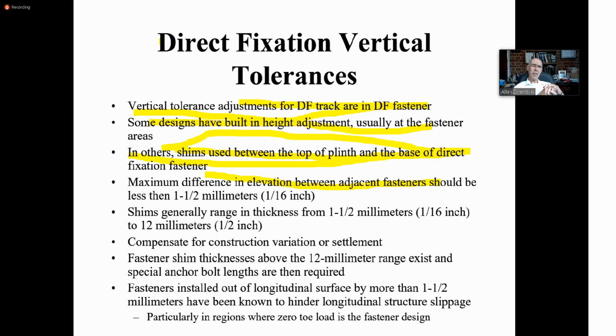And what was happening is that the elastic fasteners that they were using, which were a Vossloh fastener, were failing in fatigue very, very early on. I'm talking within the first year of service. And so they actually had 55-gallon drums on the deck of the track, where they just used to throw the broken fasteners and come in every couple of weeks and replace them, until they finally had to come back and do a complete redesign of the entire structure because it's intolerable.